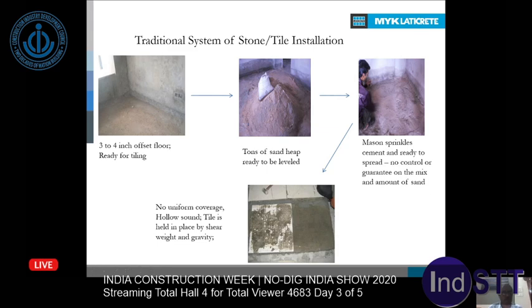Why this 3 or 4 inch? Because they want to leave this for conduits, pipes, and other systems. Then we have to fill this to have the level up to the door. So we have to fill with sand, a good amount of sand taken into high-rise buildings. Then with a little amount of cement mixed with this, they spread it. They make a very loose bed of sand and cement. They call it a thick bed, and once leveling is done, the mason sprinkles a little amount of cement, then puts a cement slurry over it, then fixes a tile over it.